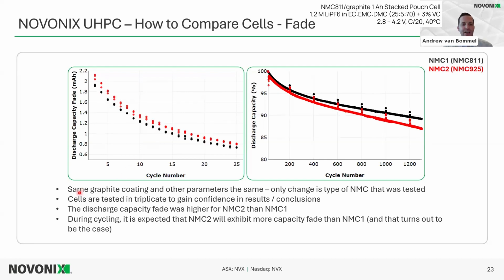In this case, just going over the cell build, the same graphite coating was used, so you can really have confidence in this. And you expect that discharge fade to be higher, and in fact it was. So it really gives you the confidence, because if you just did a bit of C/3 cycling and ended here, you wouldn't be 100% sure that it would be higher fade. But when you do even further long-term cycling, it supports what was found very early on in the UHPC test, that there's more fade from that 925 than the 811. Of course, you may want to still use the 925 if you get higher capacity, or if you can get the material, or it's a lower cost material as well.